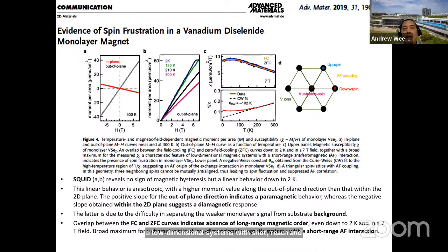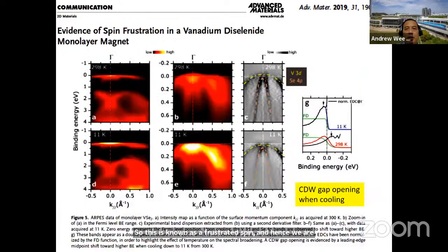So we can imagine a hexagonal lattice like this, where vanadium atoms, one could be spin up and spin down, and the ion at the center being either up or down. So this is known as a frustrated spin. And hence we are postulating that the spin in this material is frustrated. This is some ARPES data we did showing charge density wave gap opening.